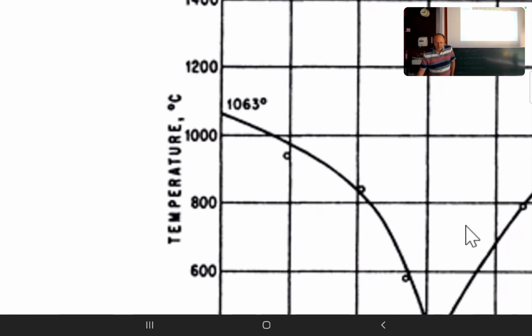And so how can we make a process? I told you, you must avoid oxidation of silicon. Silicon oxide is one of the most stable oxide we have in nature. And so when we have only a few nanometers of silicon oxide on top of the silicon and put gold on, we do not have the system of silicon versus gold, but we have this system of silicon oxide versus gold, and that has no eutectic. And on the other hand, we also need direct contact between silicon and gold in order to have an ohmic contact. Yes, we want to have conductivity.